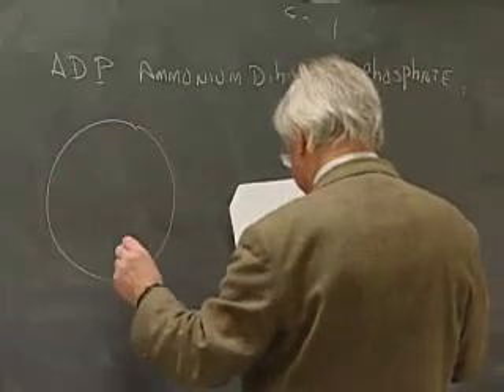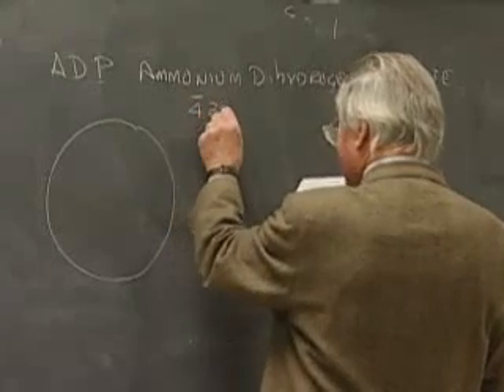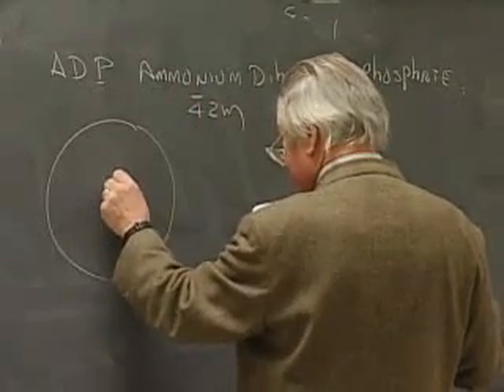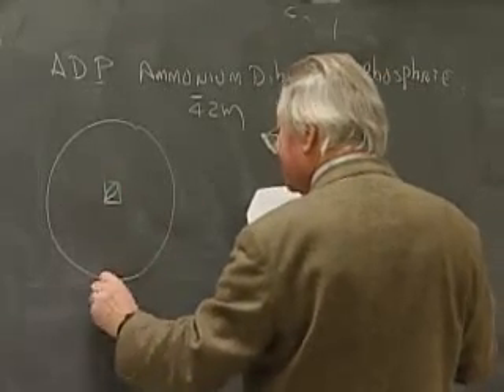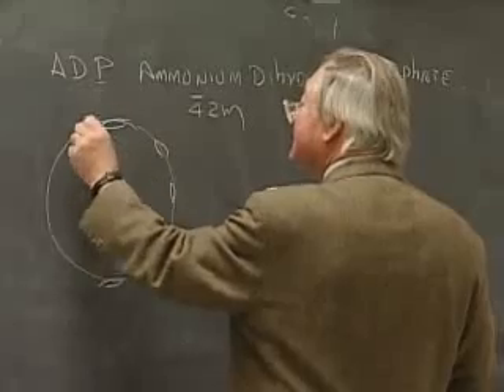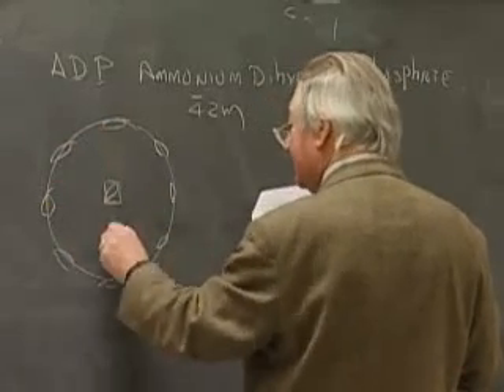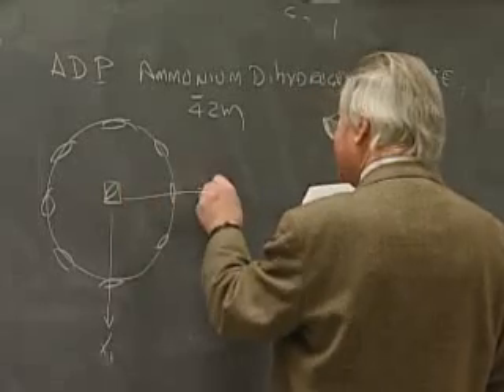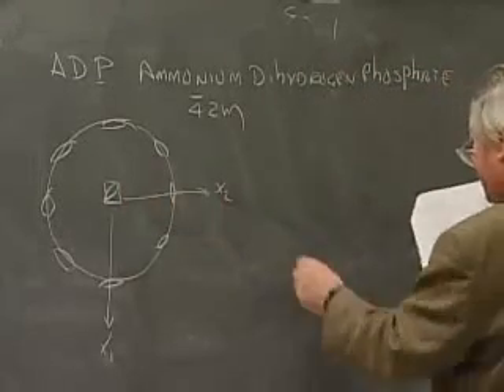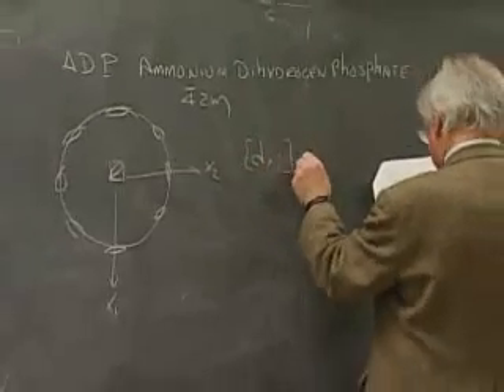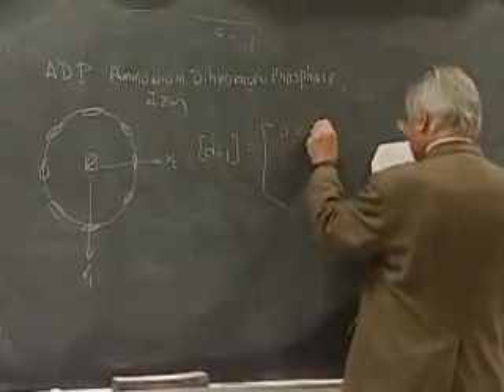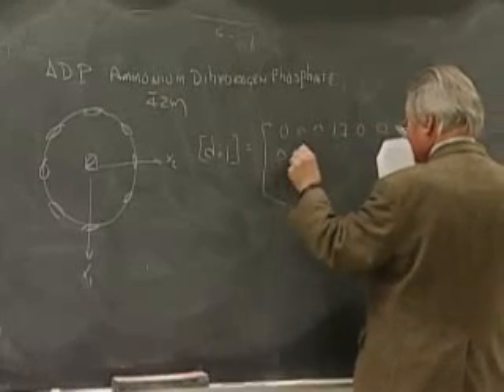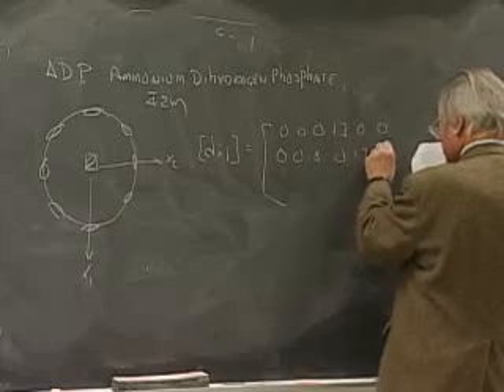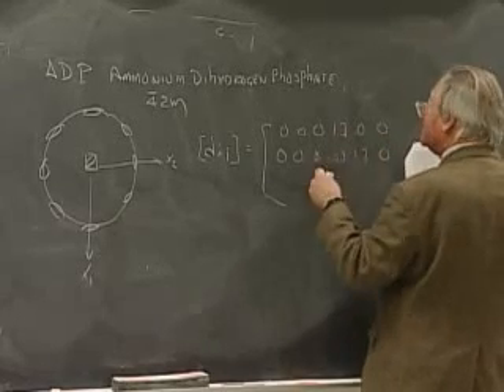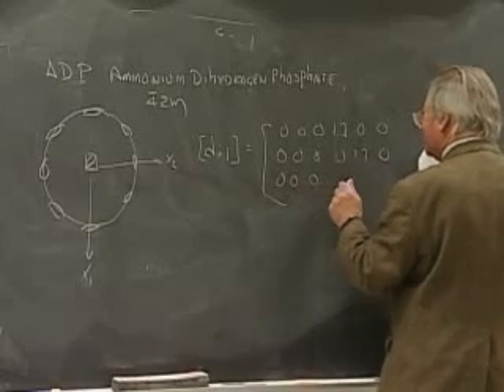But if we look at the moduli relative to the standard axes, and this has point group 4 bar 2 m, so X3 is taken along the 4 bar axis. Then there are twofold axes in orientations like this. And since they are orthogonal, you can take both X1 and X2 along the twofold axes. And the numbers here for Dij are 0, 0, 0, 1.7, 0, 0, 0, 0, 0, 0, 1.7, 0. This is one of the interesting tensors where there's a diagonal row of non-zero terms off on the right-hand side.